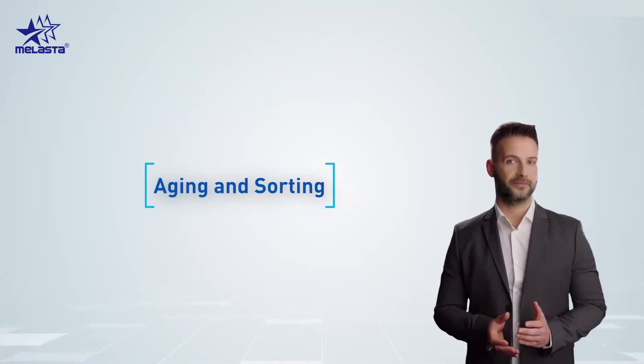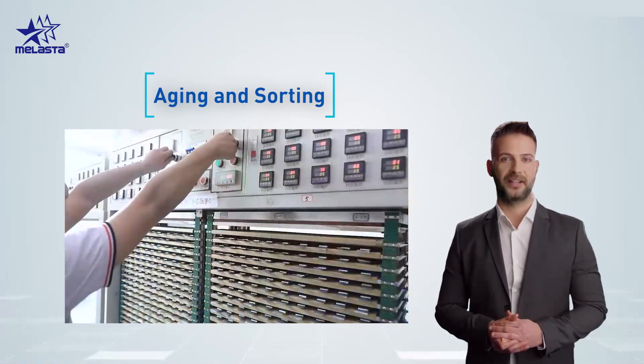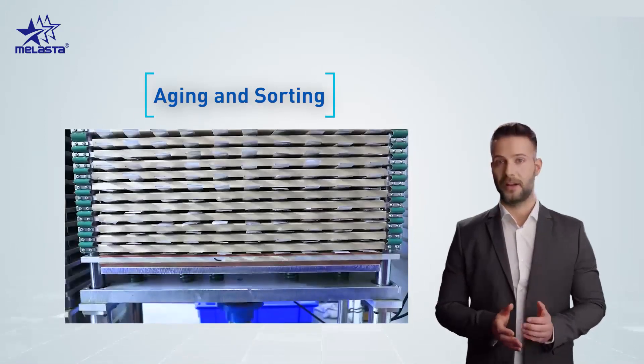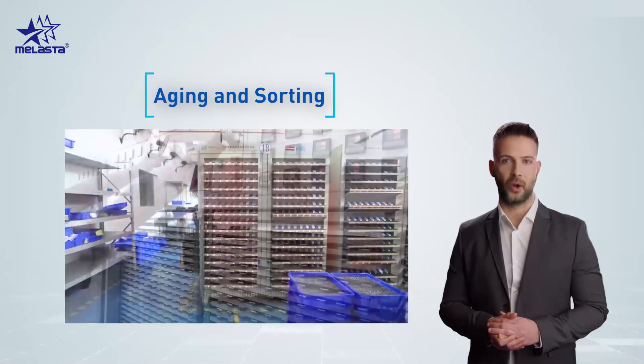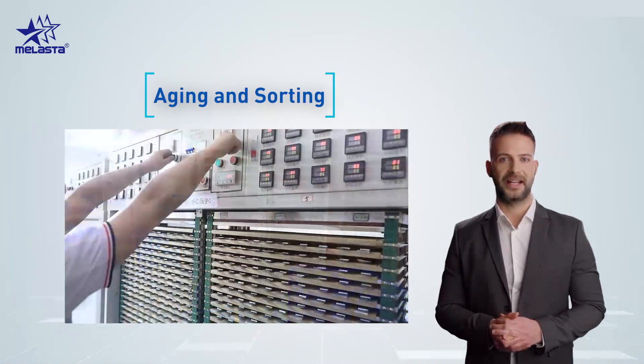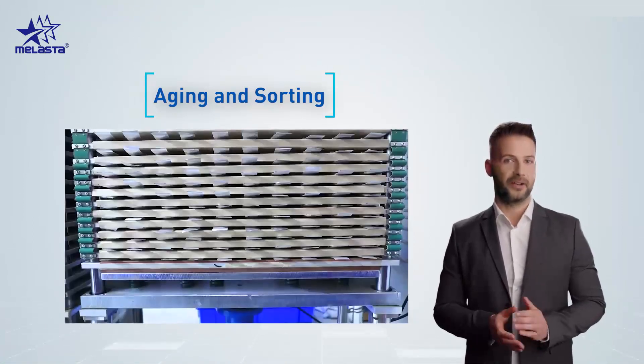The next steps are aging and sorting. Cells go through the aging and sorting process after capacity formation. Sorting is mostly based on internal resistance, cell appearance, size, and weight. Internal resistance is significant for the complete battery pack — it's vital to put all cells together having the same voltage, capacity, and internal resistance to ensure the whole battery pack is discharging and charging at the same level, ensuring the battery's safety and longer cycle life. From appearance, it is easy to judge how cells look, and if a cell does not look like normal cells, it will go into grade B. This standard is based on the cell datasheet requirements.